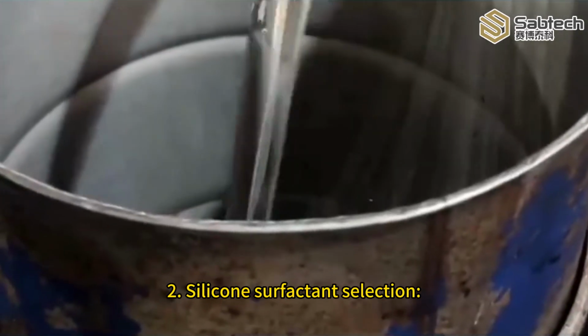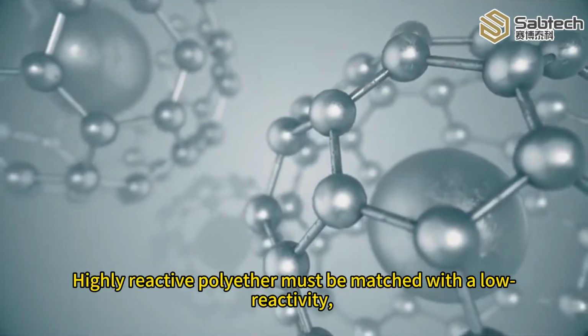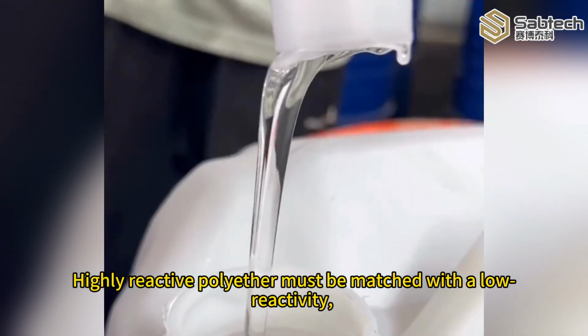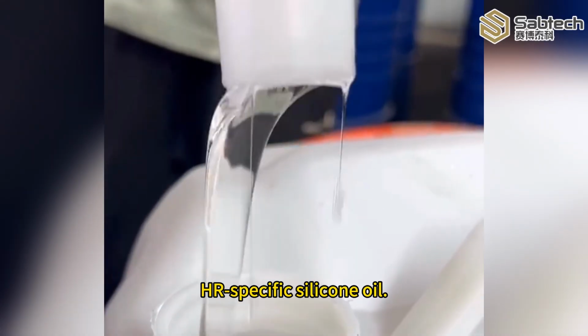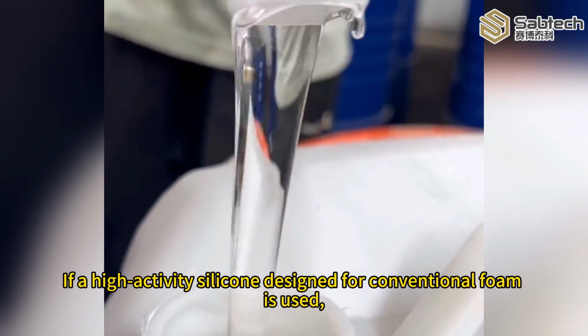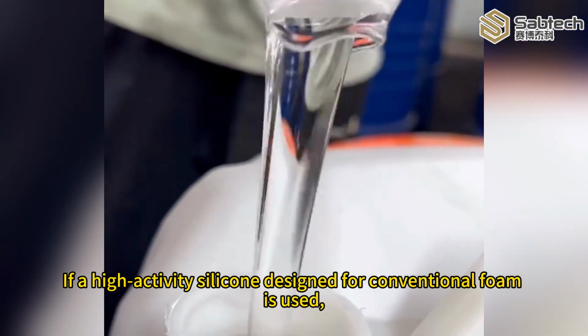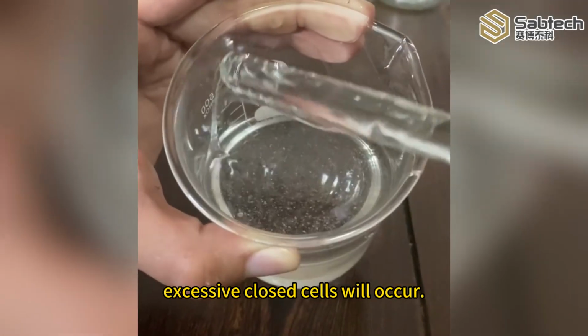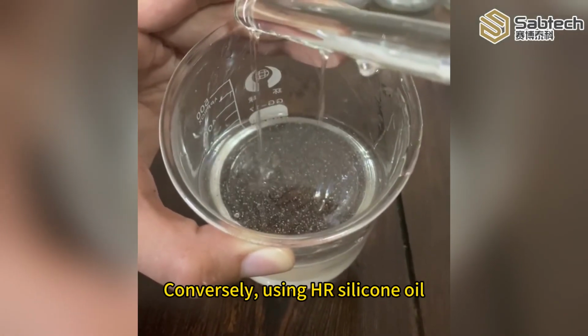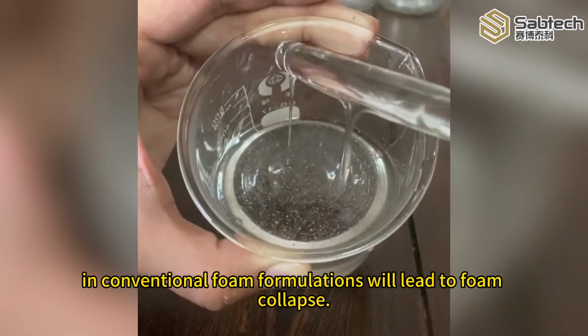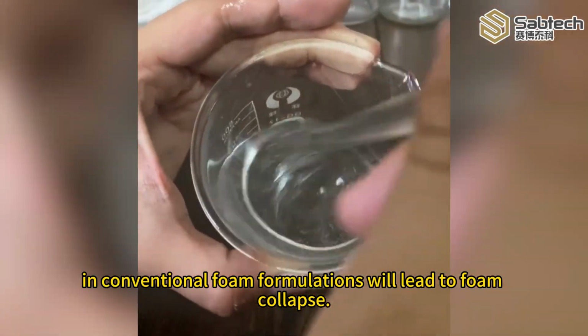2. Silicone surfactant selection. Highly reactive polyether must be matched with a low reactivity, HR-specific silicone oil. If a high-activity silicone designed for conventional foam is used, excessive closed cells will occur. Conversely, using HR silicone oil in conventional foam formulations will lead to foam collapse.